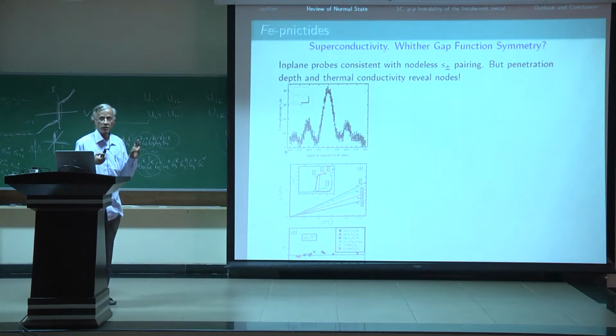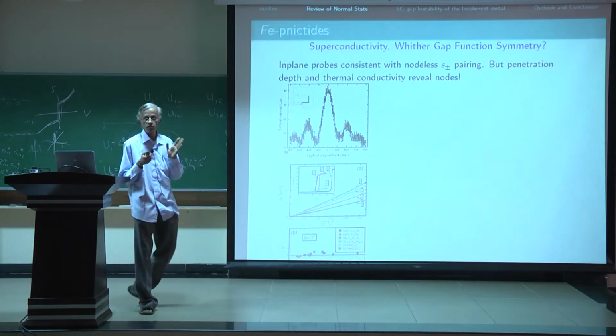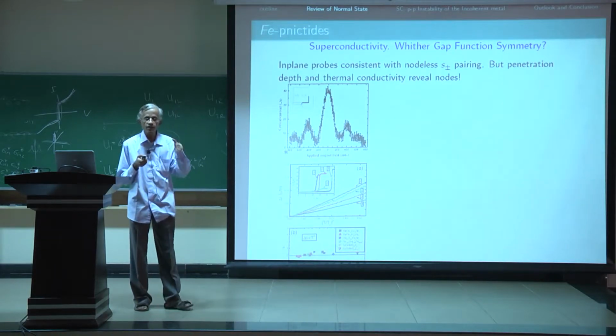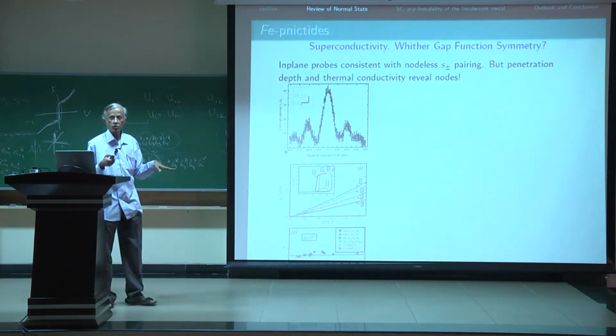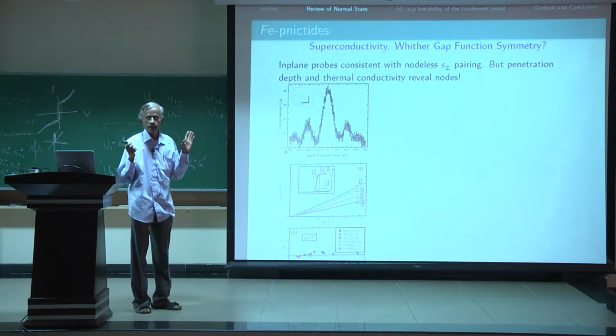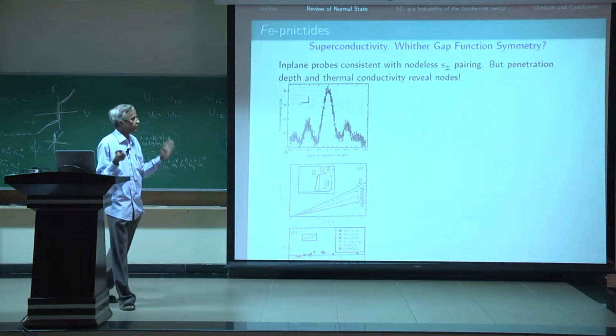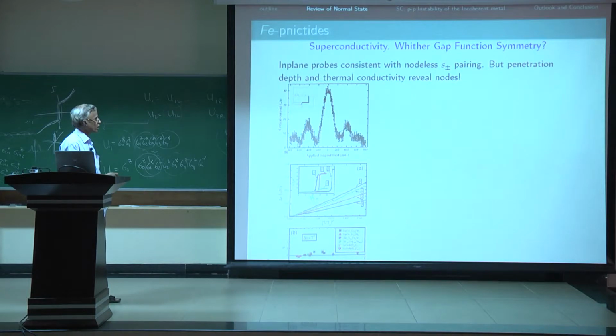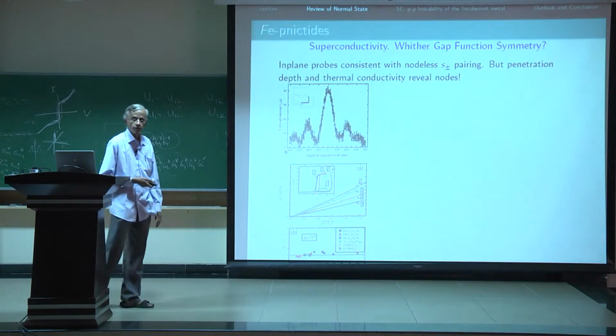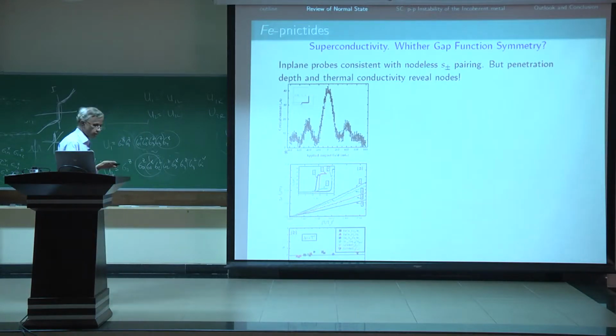Okay. So if you take some of the 1111 superconductors, the penetration depth goes exponentially as you lower the temperature to 0, which would be indicative of a nodeless gap. But if you look at the 122, which I have shown you here, and these are for different families of iron arsenides, including 1111, 122, and so on, all of them show a penetration depth which is linear in temperature, suggesting line nodes.